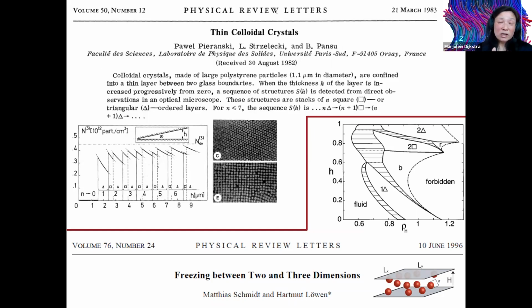And what they found was that there's an alternating sequence of triangular, square, triangular, square, triangular, square layers. So the best packing in the lateral plane you obtain with a triangular lattice, a hexagonal layer. But if you increase the plate separation slightly, then the densest packing in the transverse direction is just a stacking of two square layers. And so that's the reason why it alternates from triangle layers to square lattices to triangle layers to square lattices.